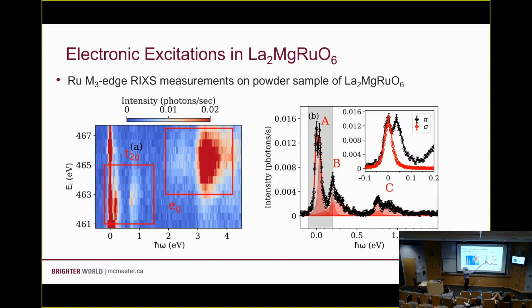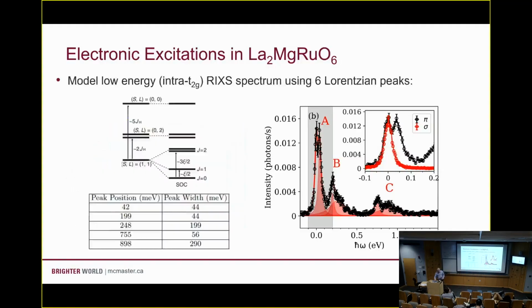Okay? So this is a scan which is taken sort of at the peak of the resonance here. It shows us the main features we've got here, A, B, and C. Okay, and what are these associated with? Well, the strongest peak here, the lowest energy one, this is going from the J equals 0 ground state to the J equals 1 first excited state. So that's our spin orbit exciton. The second peak that we've got here is going from J equals 0 to J equals 2, okay, to our second excited state. And the third peak that we've got out here, the C peak, that's going from this ground state Hund's multiplet to the first excited Hund's multiplet. Okay? So why we want to map these out is because once we've seen where these energy levels are, we can relate these directly to the microscopic terms that go into sort of single ion picture to describe this material. Okay?